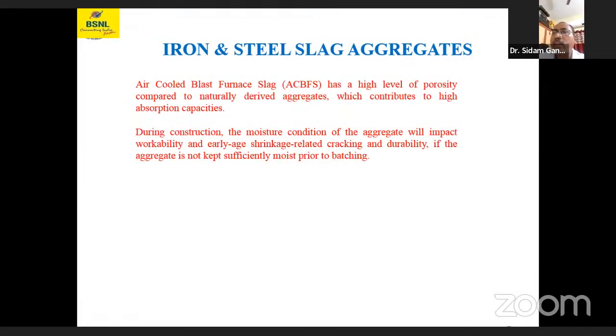Air-cooled blast furnace slag has a high level of porosity compared to naturally derived aggregates, which contributes to high absorption capacities. During construction, the moisture condition of the aggregate will impact workability and early age shrinkage related to cracking and durability, if the aggregate is not kept sufficiently moist prior to the batching of the concrete.